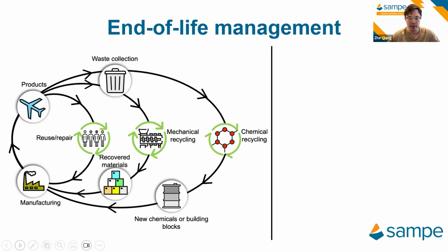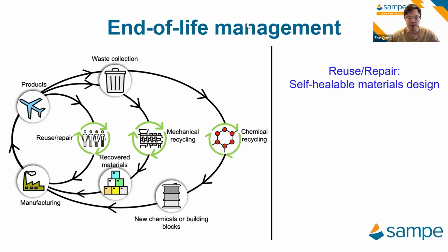Alternatively, for thermoset or crosslinked materials, a more common approach to address this is chemical recycling, which means that you do change the chemical structure of the materials. The common approaches include pyrolysis or catalytic degradation to recover these used plastics or used crosslinked materials into new chemicals or building blocks, and then build them back into the manufacturing process. So in this case, as you can see here, they may cause more energy consumption as well as cost.